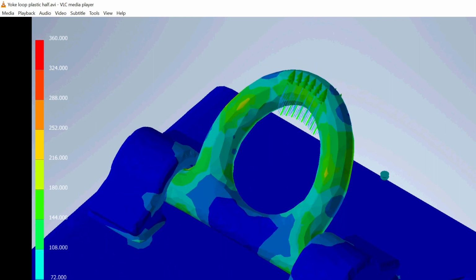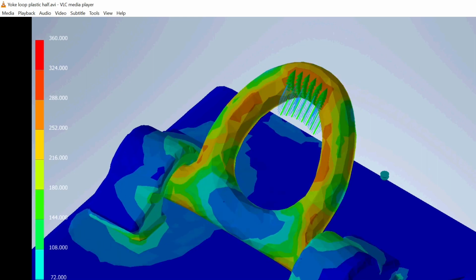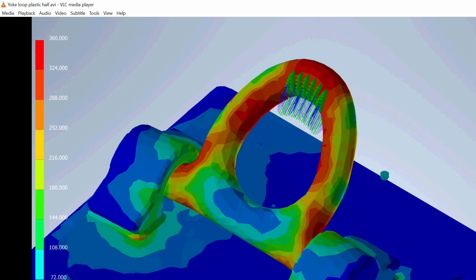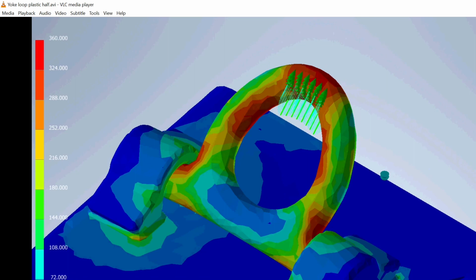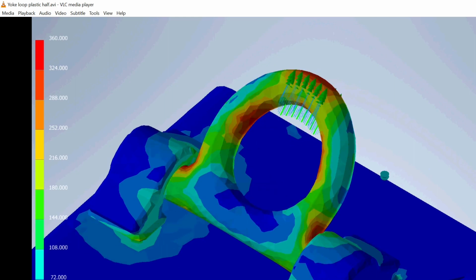But then that produces residual stresses. So if you have a different loading condition, you have to consider adding up these residual stresses from different loading directions if you're going to work in a plastic range. And also, if anything is happening within the plastic range, that's a recipe for cyclic loading sensitivity. So frequency stress limits, cyclic stress limits, they should be checked on that as well.